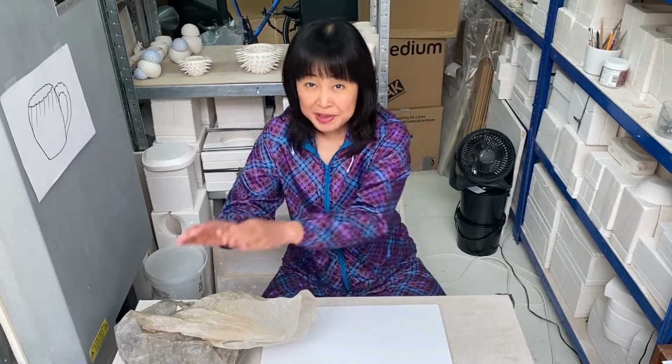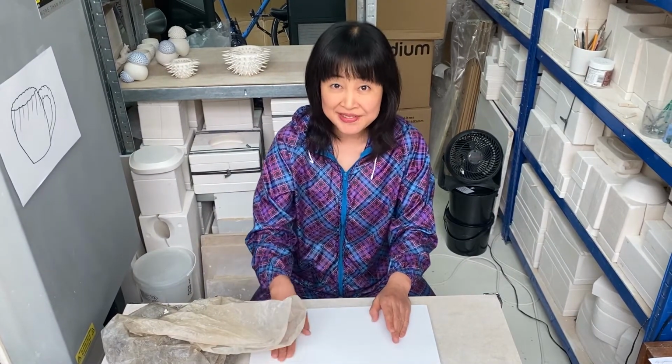Right, the first thing to do is plaster model making. When it comes to model making, you have to take shrinkage of your work into account. After high temperature firing, your work of porcelain will come out of the kiln with roughly 15% smaller size. So don't forget to create your model bigger than the actual size you are looking at. Anyway, let's get started. We use backclay to build the wall on the flat board with a slick surface.